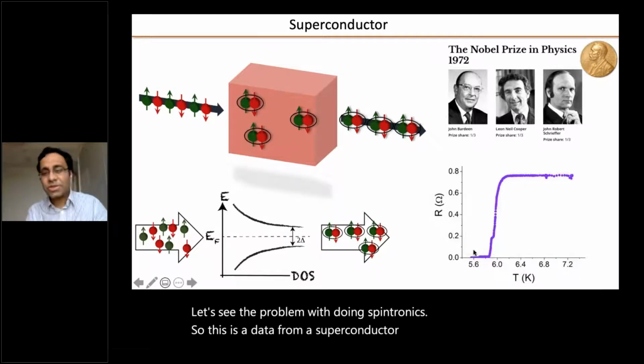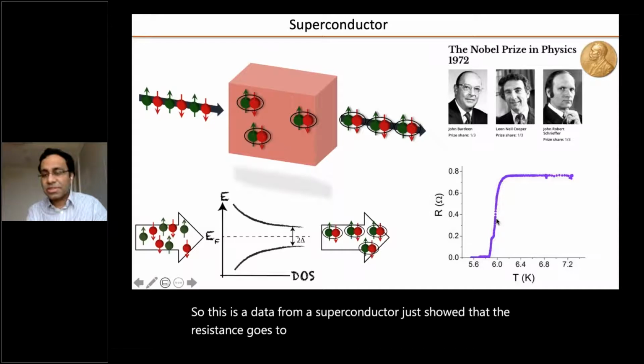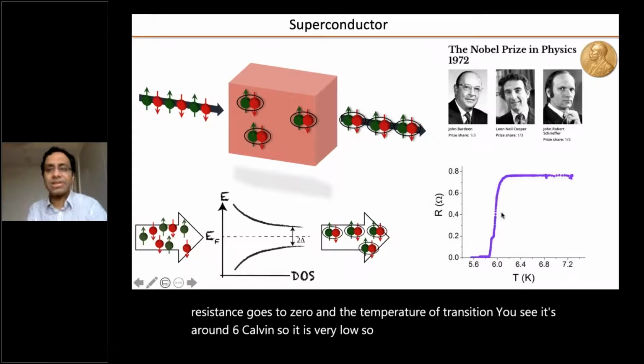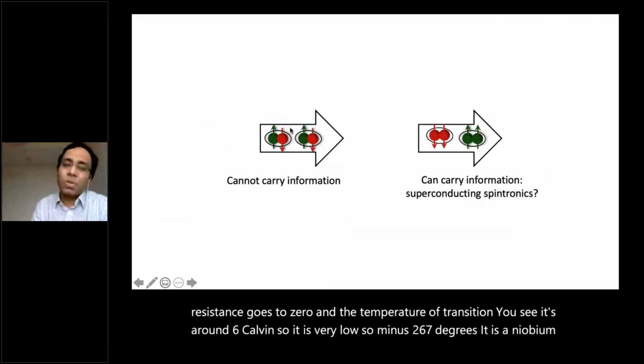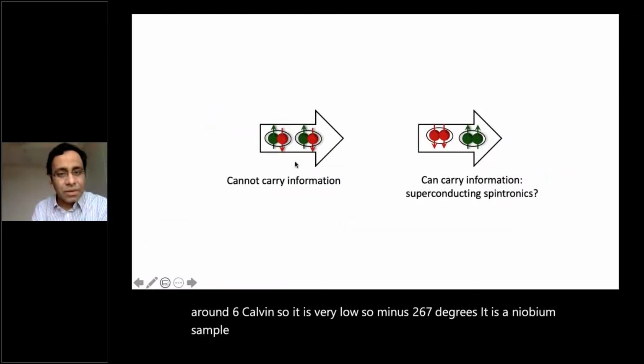So this is data from a superconductor. I showed that the resistance goes to 0, and the temperature of transition, you see, is around 6 Kelvin. So it is very low, minus 267 degrees. It is a niobium sample. Okay, now, so what do we have?